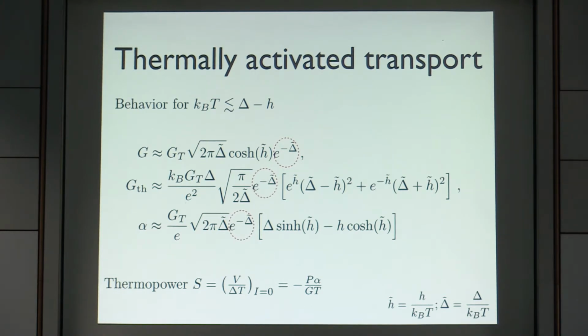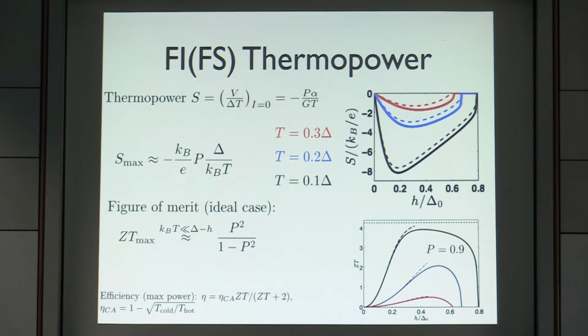Now, this means that the thermoelectric current in our setup is finite, but it's small. But not the thermopower. Thermopower is something where, instead of a current, you measure a voltage in an open circuit configuration where the current vanishes. This is just the induced voltage divided by the temperature difference, and it is given by the ratio between this thermoelectric coefficient and the conductance. In this case, you see that the exponentials cancel out, and the thermopower should be very large in these systems. In fact, it's not even of the order of unity, it actually diverges, like 1 over the temperature in this case. Obviously, there are some effects that then limit this divergence at very low temperatures, but I will not go into them.